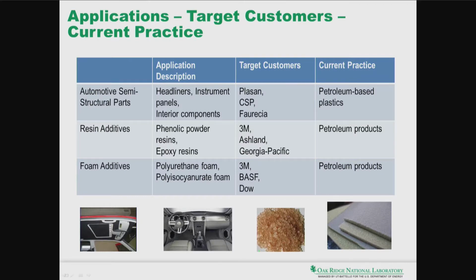So let us now look at the target customers for this particular technology. As we are talking about, this is a resin equivalent to ABS resin, so it can be used for automotive structural part manufacturing. And in fact, we talked at some point with some of the researchers in these companies. Of course, it can be used as a resin additive or resin modifier, for example, for phenol formaldehyde resin, where lignin can be used. But we are not necessarily talking about those kinds of thermoset resin. The polymer that we are synthesizing can be used as an additive in other material. In fact, we have demonstrated that under certain conditions, lignin itself can replace almost 40% of ABS resin under certain compatibility conditions.